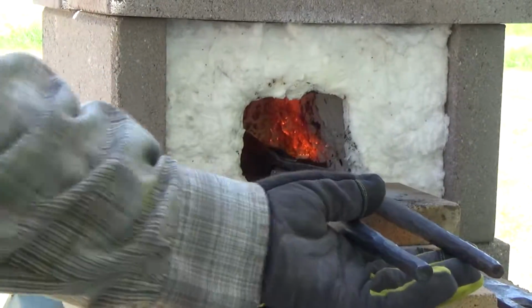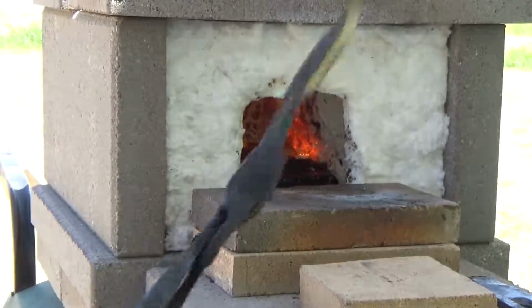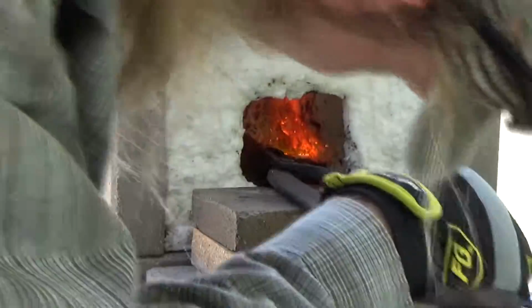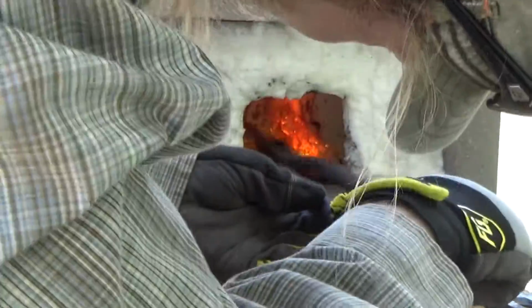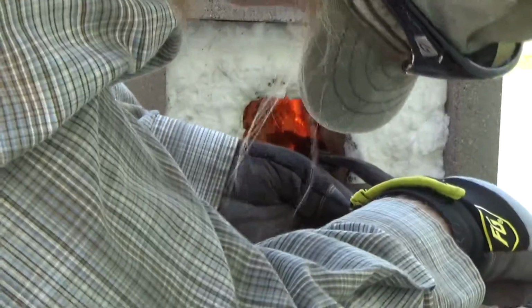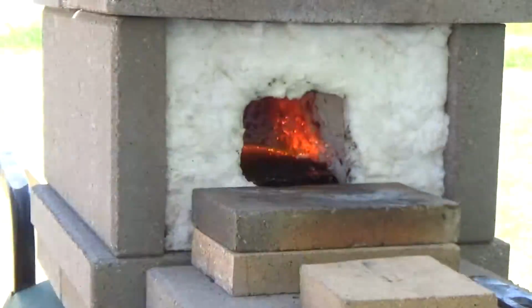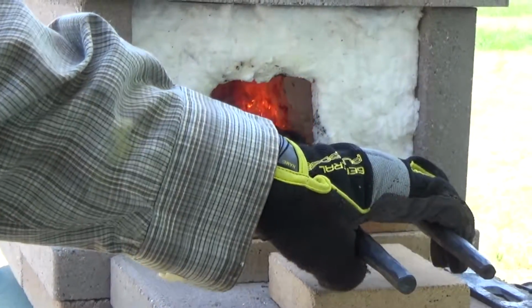So a triple quench involves heating it up to approximately non-magnetic or just above to this particular steel's critical or austenizing temperature, and then quenching it to below 900 degrees, which is essentially taking it from the heat treat temperature past the pearlite nose, which is at 900 degrees, and then putting it back in the forge. Then you do that again, then you put it back in the forge, and then you do a final hardening, make sure that it's straight, and then let it cool to below 400 degrees, which completes martensite transformation from austenite.